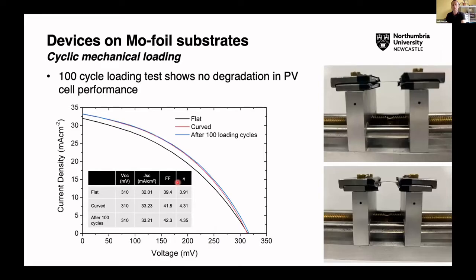We're also able to flex these cells. So the image on the right here shows the device in the flat state. This is in the curved state with a radius of curvature of about 6 centimeters. And we don't see really any big difference in efficiency, no degradation between flat and curved state. And then interestingly, when we cycle these in a loading or a fatigue type test, the devices hold up pretty well indeed. So we don't see any degradation as a result of 100 cycles. So that's encouraging.